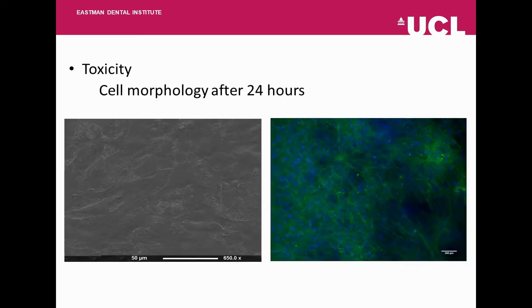We also were interested to see the cell morphology, what the cells look like. Are they happy on the material? The image on the left is a scanning electron microscope image taken where cells were attached to the disc, and also staining with DAPI and phalloidin was done to see the presence of cells after 24 hours. The cells show they're spreading out and they're happy and they're flat. So this is a good sign that our material creates conditions where cells will be happy to stay.